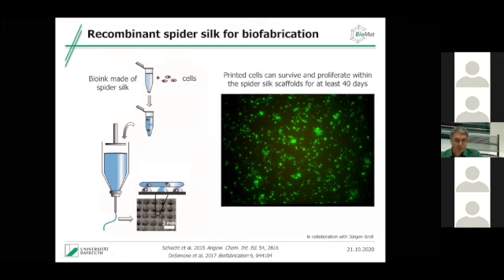And the first thing we looked at was, do the cells survive that? Because if you just print cells without any scaffold, most of the cells die. And here you see a live-dead testing after 40 days. You see a lot of green dots, and probably you see no red dots. A red dot would be a dead cell. All the green dots are living cells. So we have a survival rate here in the printing process of more than 99%. So actually the silk gel is not only the scaffold where the cells sit in, but it also shields the cells during the printing process. It shields the cells from the shear stresses, from the elongational stress that appears down here at the needle. And this actually allows us now to 3D print cells with the scaffold, and they're surviving that.